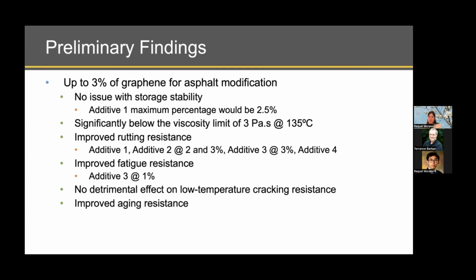We saw that in terms of improving fatigue resistance that occurs at intermediate temperatures, only one additive showed a pass and fail temperature lower than the base binder, that was additive 3 at 1%. However, the pass fail temperature that resulted from the binders modified with the graphene products were not significantly higher than the base binder. We did not see a detrimental effect for any of the additives at the 3 doses evaluated in terms of cracking resistance at low temperature.